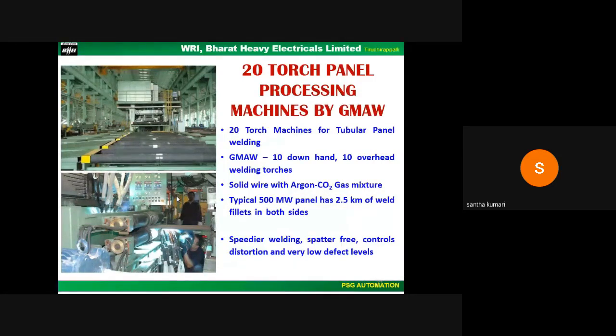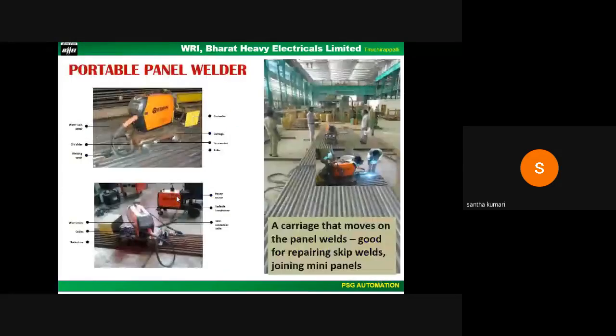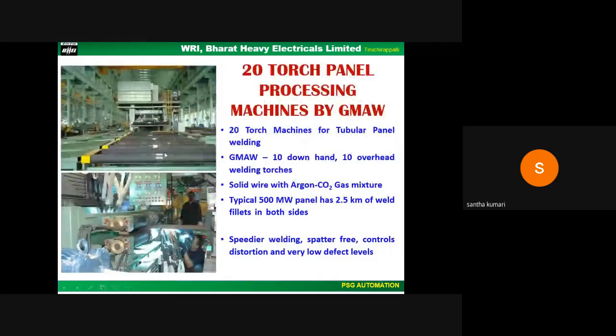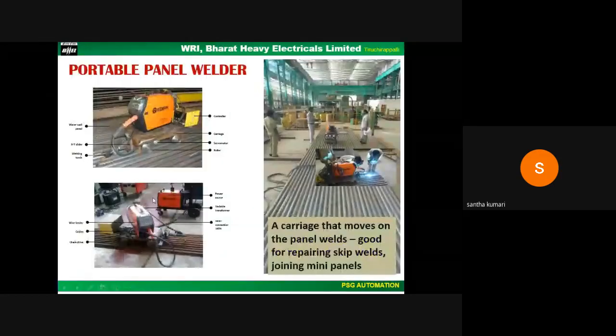During the panel welding, the next slide would be panel welding. Sometimes we have issues, as I said, with this 20-torch machine. Even sometimes we have issues of skip welds, because it has to continuously weld 2.5 kilometers of fillet weld. So sometimes the skip weld will be there. Hence, a carriage-mounted welding system that will move on the panel has been developed for repairing the skip welds and also for joining mini panels, by which we were able to save